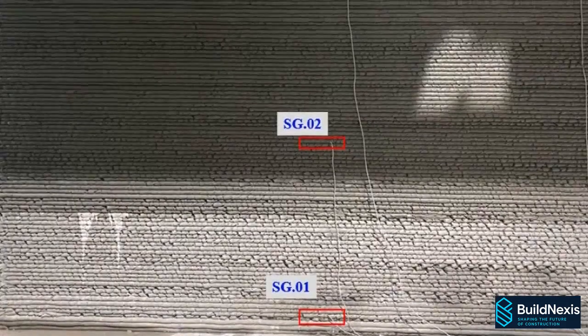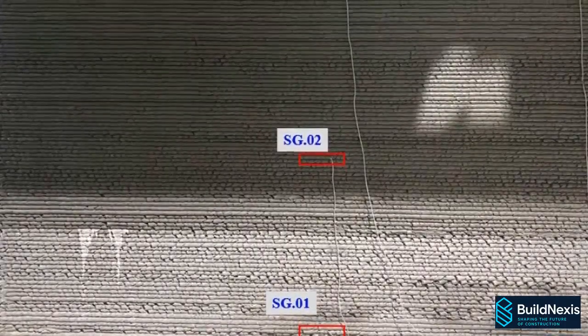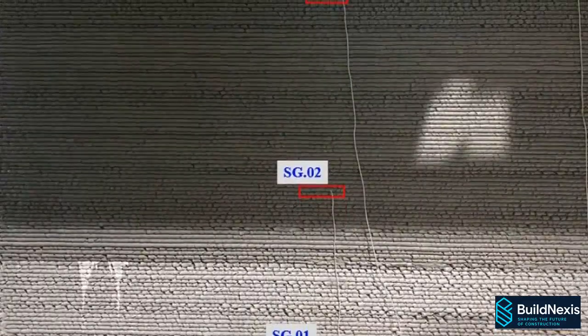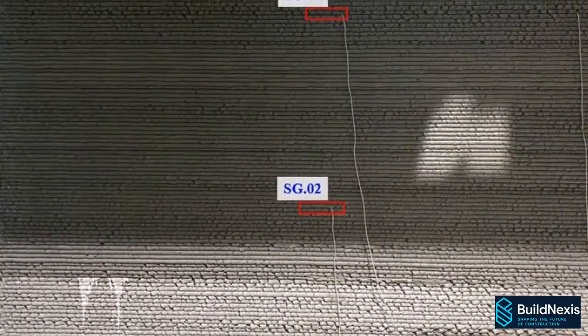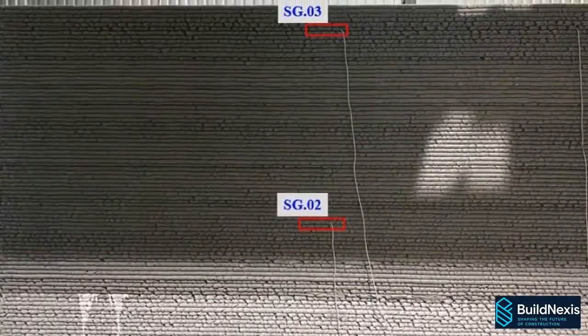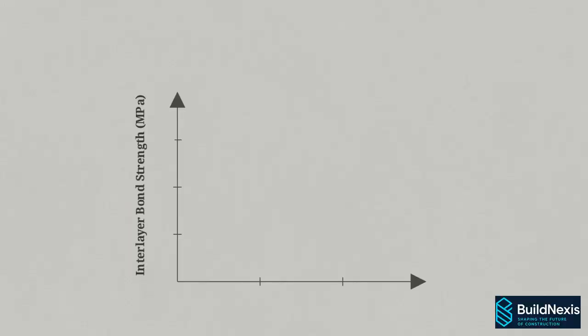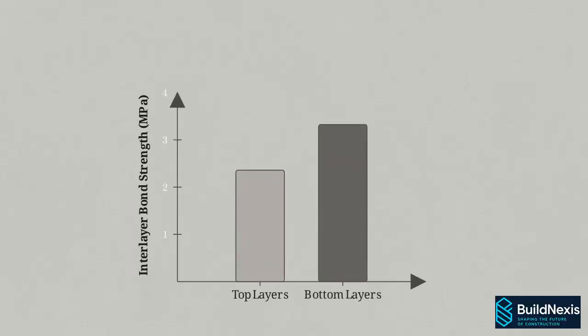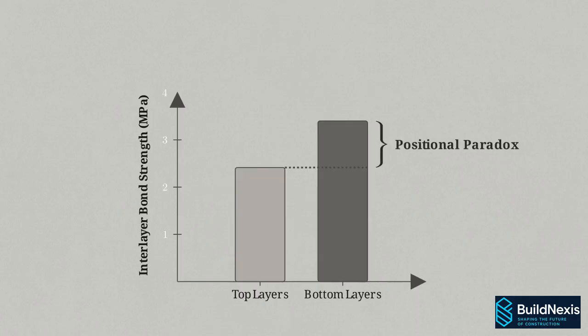During the extrusion process, strain gauges were embedded directly into the concrete filaments at 3 specific elevations: the 5th layer near the bottom, the 50th layer in the middle, and the 95th layer at the top. The data revealed a positional paradox. The bottom layers of the exact same wall exhibited significantly higher interlayer bond strengths than the top layers.